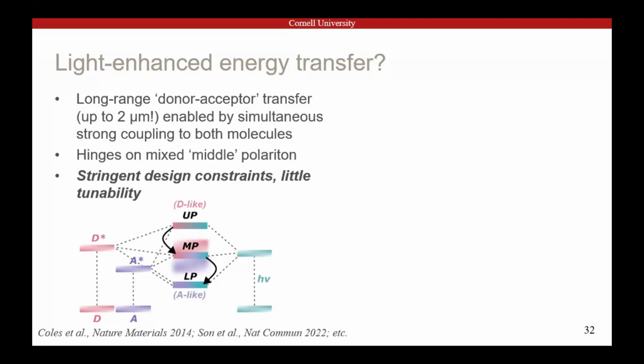Quite remarkably, this concept works even if the donor and acceptor molecular layers are separated by as many as 2 microns, way beyond Förster's wildest dreams. So this is really long-range coupling or interaction between the molecules mediated by the cavity. But it's also kind of cheating, because this is not a donor state, this is not an acceptor state. All of these states are mixed together. So it's really a new quantum system.